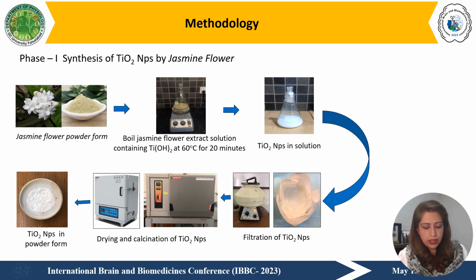After 24 hours, these deposits settled at the bottom and were washed with the ethanol and deionized water to remove any biological extract left behind in it. These titanium oxide nanoparticles were completely dried in an oven at 80 degrees centigrade for about next 2 hours, and then calcination was carried out in a furnace at about 450 degrees centigrade for 3 hours to get finely powdered form of titanium oxide nanoparticles.